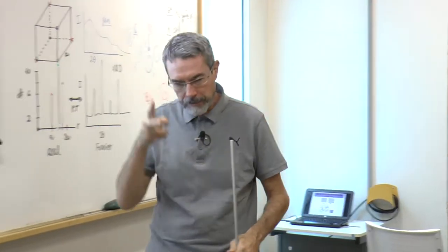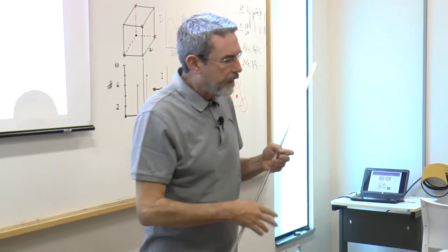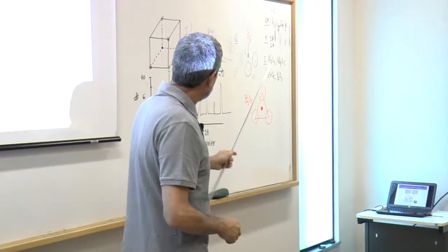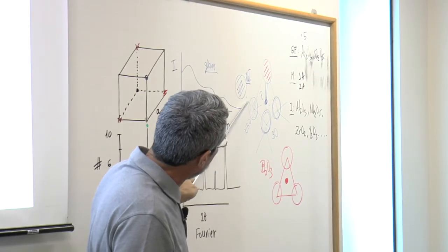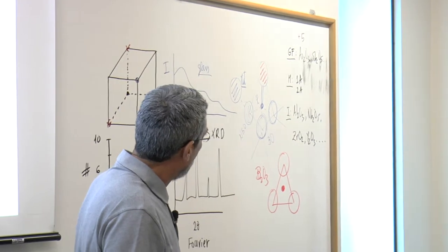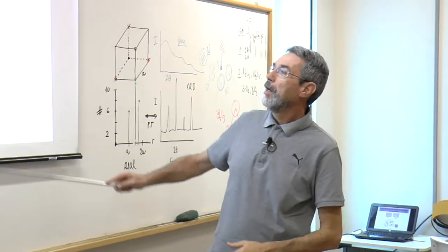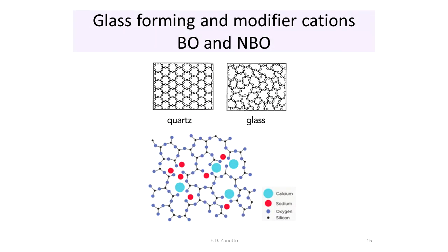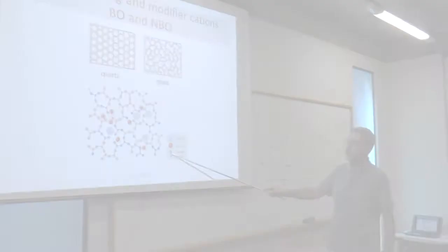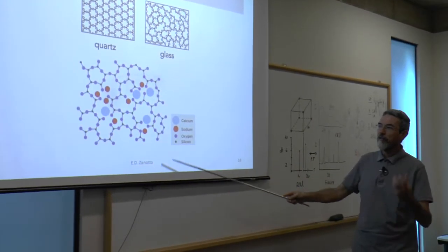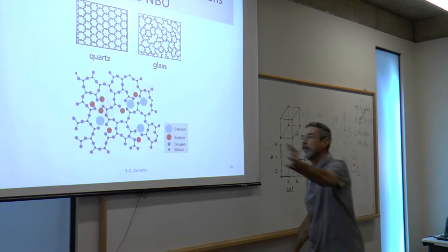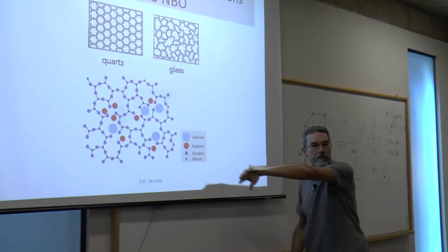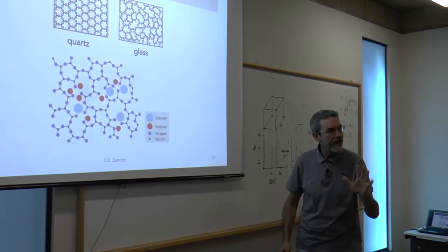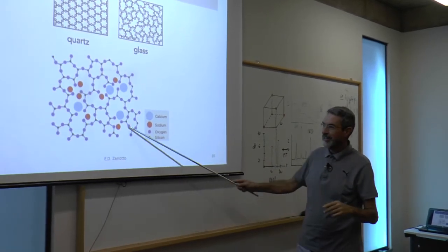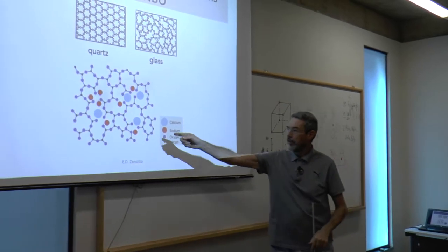So each atom which is added, it's like a scissor that cuts these bridges and forms non-bridging oxygens. And this is a nice picture here. In this picture, we have sodium, silicon, oxygen, and the fourth oxygen is hidden below that plane or above that plane. So they're tetrahedral, but in this planar drawing, they seem to be triangles, but there is a fourth oxygen which is hidden.